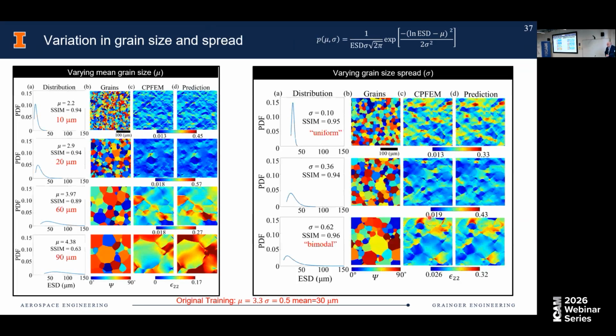All right, so load. What about, I'll just run through these quickly, what about grain sizes? Grain distribution. Well, it's the same distribution, just changing grain size through this log normal distribution, either average grain size or changing the sigma, it kind of goes from uniform to bimodal. Again, extrapolation works a little bit. It works for smaller grain sizes pretty well. It was trained at 30. It works pretty well for 20 and 10. As you move to larger grain sizes, it started losing it, in part because you now no longer have RVEs when you're down to this type of grain size, right? So that is what we kind of identified as an issue.